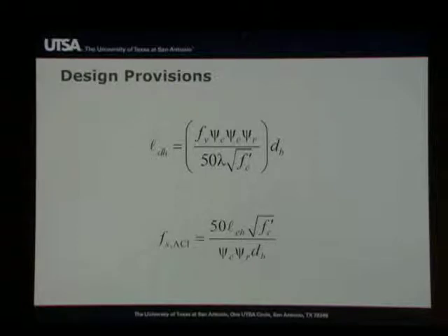These are the equations in the ACI code that are not significantly different from the AASHTO code. Of course, in the ACI and in the AASHTO, we're concerned about determining a development length for the hook. In our case, when we analyze these tests, we prefer to do the comparisons in terms of the stress in the bar when the failure occurred. So all we do is a simple piece of algebra where we solve for Fy and move it to the left-hand side of the equation. And this is the very same equation, but now it gives us an equation for stress. And this I'm going to label stress ACI is what one would calculate with the ACI equation, similar to the AASHTO equation. There's no difference in that respect.